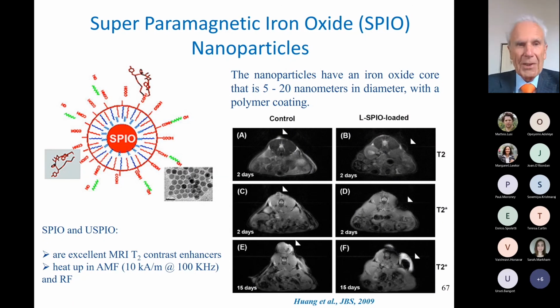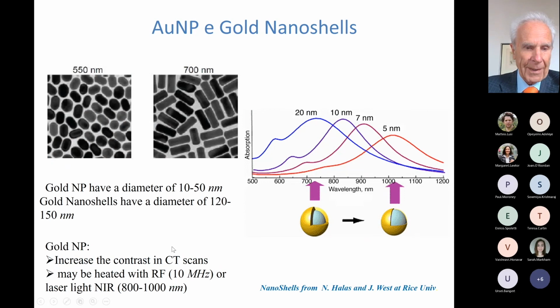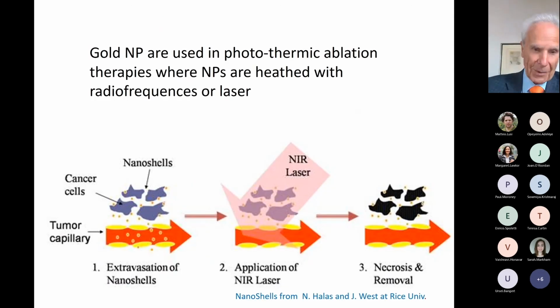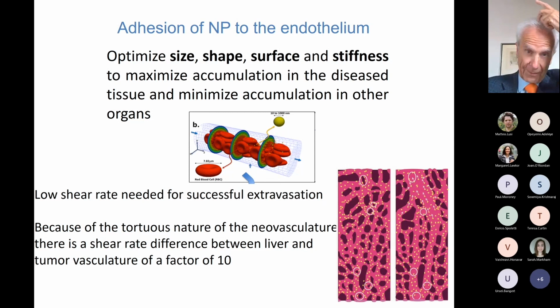Then these are interesting for the future, the superparamagnetic iron oxide, because they are excellent contrast enhancers in MRI, but they heat up with alternating magnetic fields and radio frequencies. And the same is true for the gold nanoparticles. Again, they increase the contrast in CT scans, but can be heated with radio frequencies and near-infrared laser. So with this, you can do hyperthermia. I mean, you again have to deliver them, to bring them to the tumor. Then you apply this near-infrared laser, for instance, for gold nanoparticles. You kill the tumor cells, and then they are taken away by the macrophages. Okay, that I still have to model.